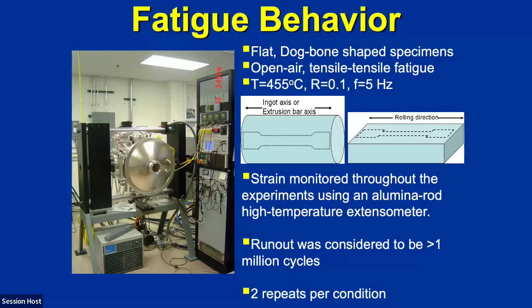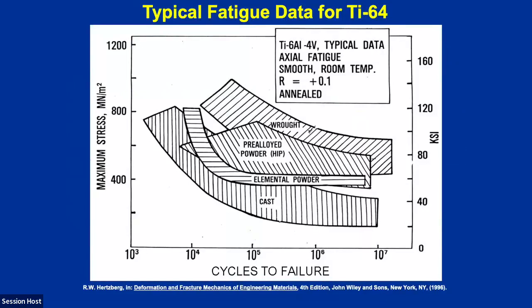So we did a lot of testing at 455 degrees C, tensile type of testing with an R stress ratio of 0.1, meaning we never went into compression, 5 hertz frequency, 2 repeats per condition. And before we started the test, we had this type of information for titanium alloys: typically wrought titanium alloys are going to be orders of magnitude higher in fatigue life at the same stress level than cast materials, where powders would sit somewhere in between. So how would this translate?